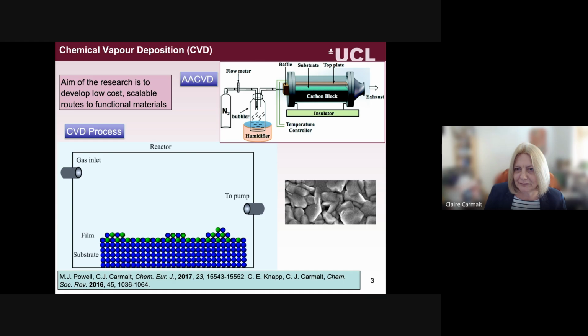Now, traditional CVD takes place either as low pressure CVD, so you would have a vacuum pump, and so I'm just going to get a laser pointer. So you'd have a pump and your byproducts could be pumped away, or it's often done under atmospheric pressure, and so you would have a carrier gas such as nitrogen. And it's the atmospheric pressure CVD, or often known as APCVD, that's used commercially by Pilkingtons to deposit the functional coatings on glass. So with APCVD, the byproducts would be taken away by the carrier gas.